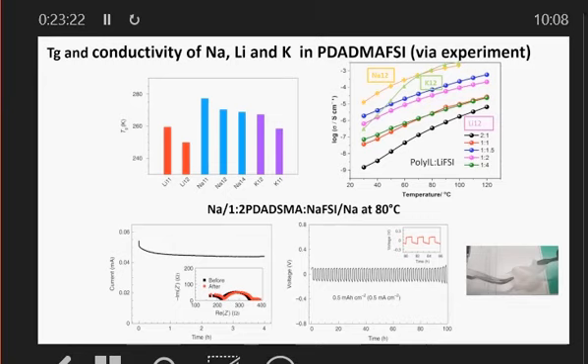So you can see the sodium has the highest conductivity in practice, which correlates with what we see from the MD simulation diffusivity. We can't measure diffusion of sodium using PFG because it's a very hard nucleus to measure diffusivity of, but from the MD simulations, we see the conductivity agrees. It's a factor of 10 higher in the sodium case. And indeed, when we made the cell, the transport number measurement here shows a fairly high steady state current and a very small drop from the initial. The Bruce and Vincent method really says how much current you lose, how much you polarize when you apply a potential.